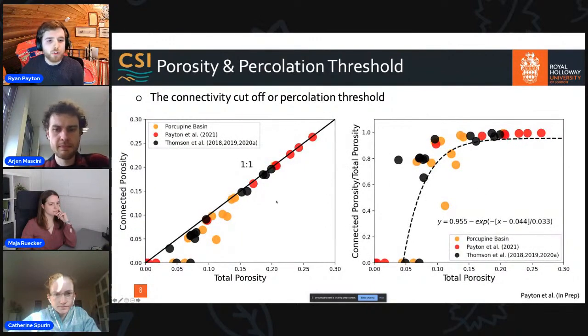We've been able to look at this in a little more detail by plotting the results from the Porcupine Basin. As I was mentioning earlier, the majority of the data points were around that 10% mark, so we were hoping it would better define that percolation threshold. We can see there's good agreement up here following the one-to-one line, but down here there's a bit more deviation, and these data points a little bit further up, maybe around the 13 to 14% mark. So we're hoping that with time, as I analyze more samples, we'll be able to better constrain where this percolation threshold is, as it's such an important value to characterize reservoirs with.